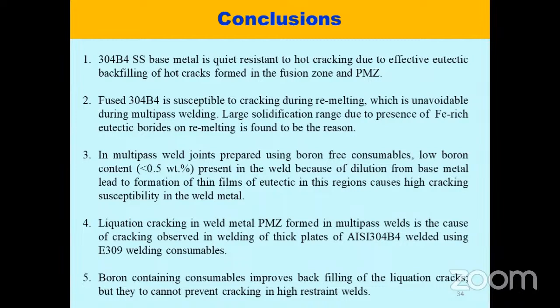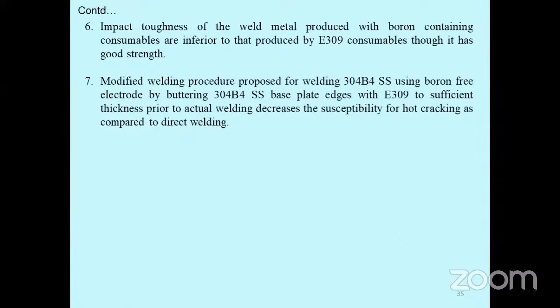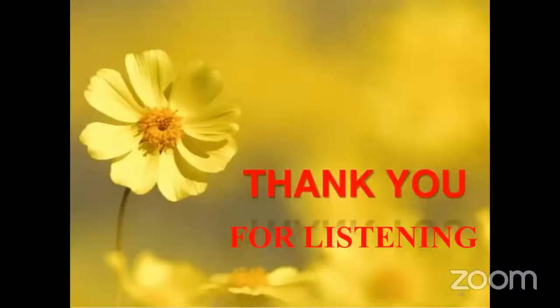So in the case of these boron-free consumables, base metal dilution plays an important role in introducing cracking in the weld metal, and this can be avoided by adding a suitable modification in the welding procedure, that is by adding a small step of buttering before the actual welding process. This is found to be very beneficial, and this is the way we have solved this problem of hot cracking in the borated stainless steel. Thank you.